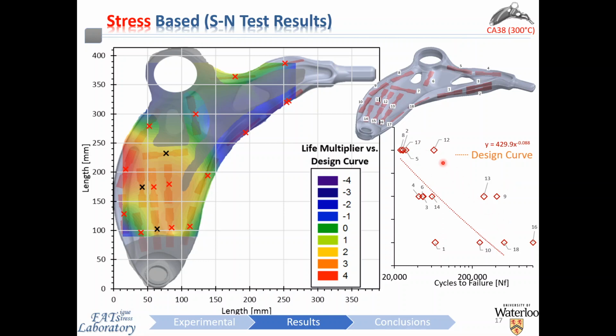So if we non-dimensionalize these data points, with ones that fall to the left being kind of worse than the idealized response and ones that fall to the right being better, once we non-dimensionalize these relative quantities, we can effectively get a life multiplier that describes how much each location deviates from this idealized response. So these are the life multipliers here shown on the contour plot, we can then map these onto the various locations of the control arm and understand the spatial variation.